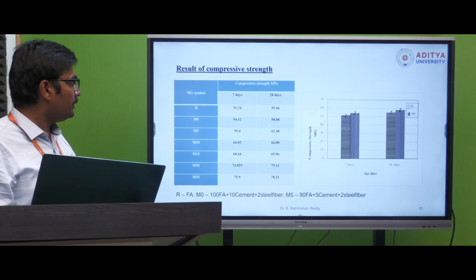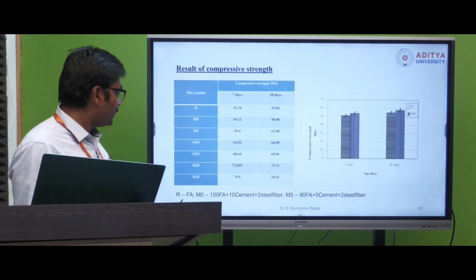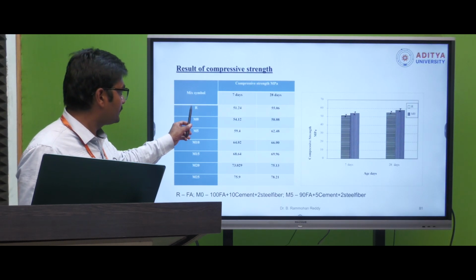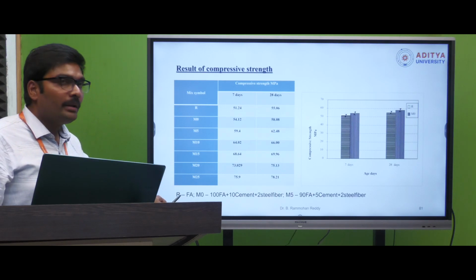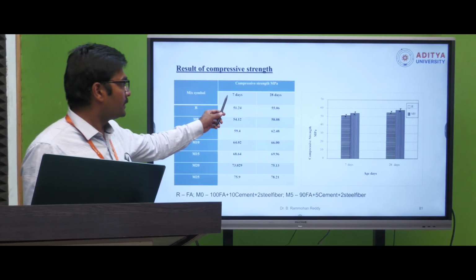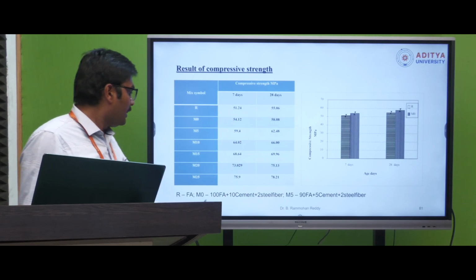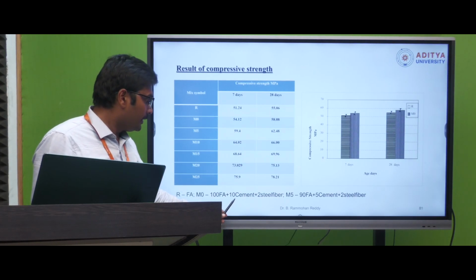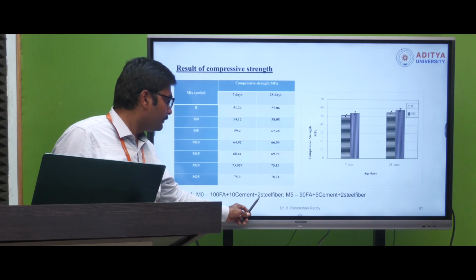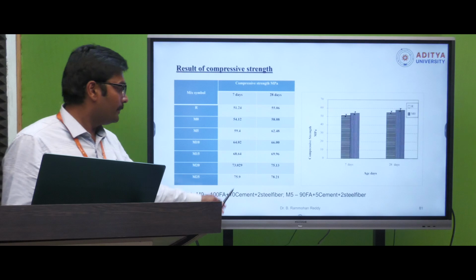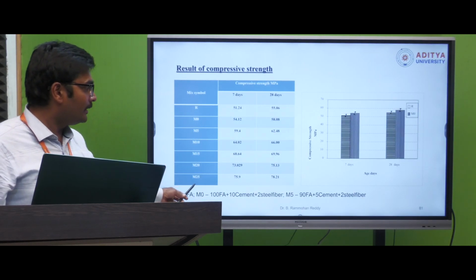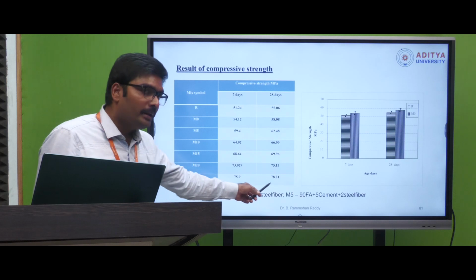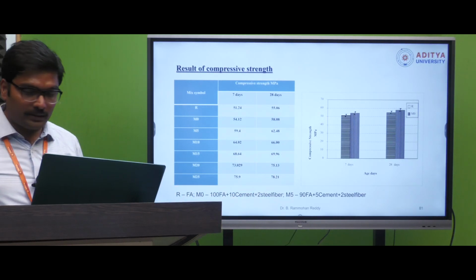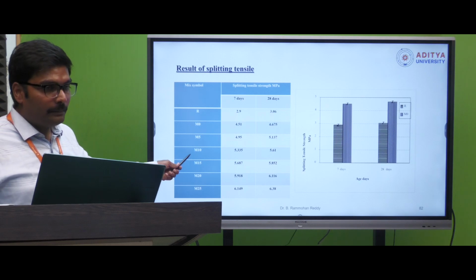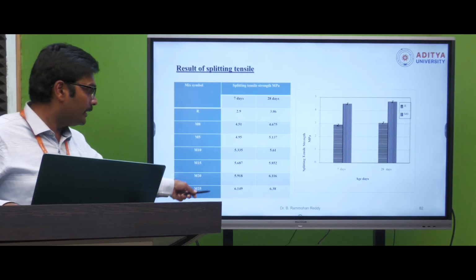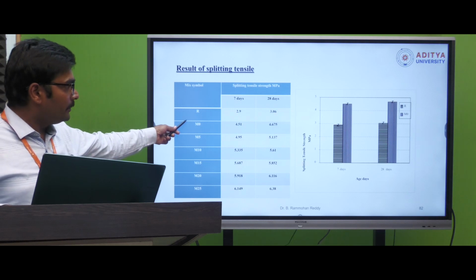And coming to the compressive strength, based upon the material which you are choosing, for example, this is one of the mixes, where R indicates 100% fly ash. If you use only fly ash, you can see the compressive strength for 7 days and 28 days. And if you replace fly ash with cement, plus 10% cement plus steel fiber, you can see that as you increase this content, the strength properties also increased. That was presented by one of the authors. Similarly, the same author presented splitting tensile strength, and how it is increased by replacing cement.